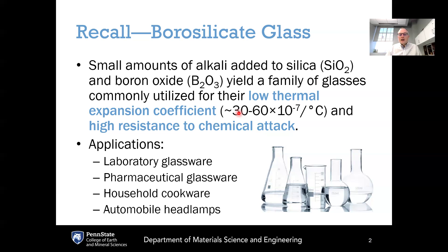Borosilicate glasses also have higher resistance to chemical attack because they have a higher fraction of network formers compared to network modifiers. For these reasons, borosilicate glasses are the choice for laboratory glassware — your glass beakers and flasks in chemistry lab are generally made from borosilicate glass. It's also the glass of choice for most pharmaceutical glassware, though some aluminosilicate glasses have also been proposed. Borosilicates are still the dominant choice at this point in time.